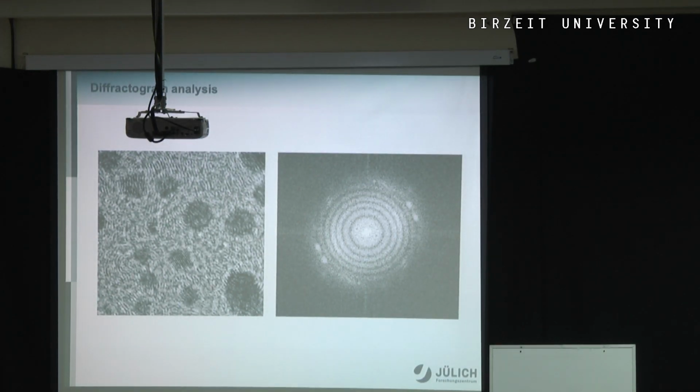Well, on the left of this slide, what I'm showing is an image recorded in a non-aberration corrected electron microscope of an amorphous thin film with some small particles of gold on it. So each of these particles, which look dark here, is perhaps 2 or 3 nanometers in size. You might occasionally be able to see some atomic planes. And then in between you have what looks like an amorphous region, and this is an amorphous carbon support film which underlies the small metallic particles.